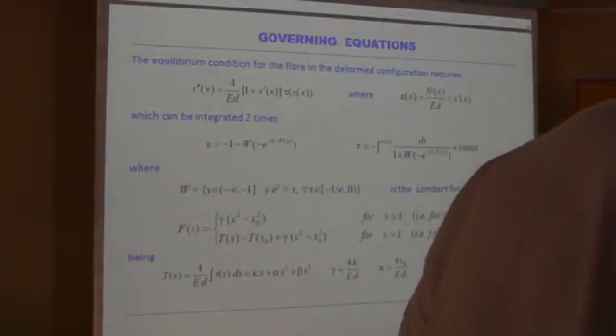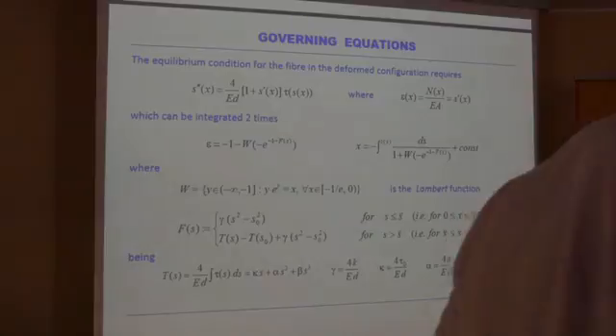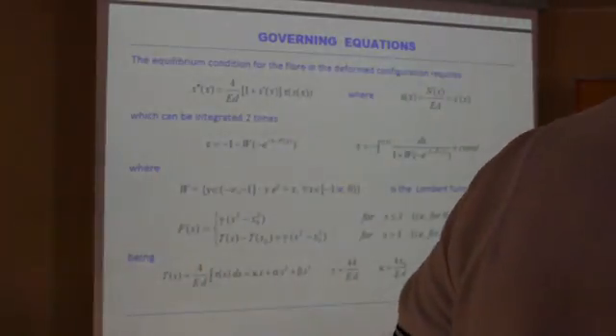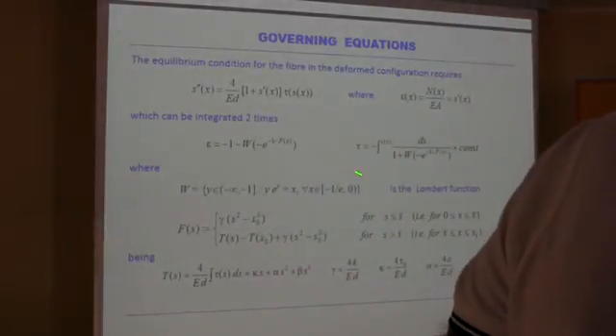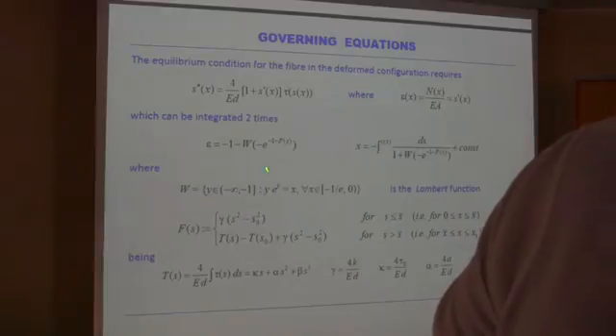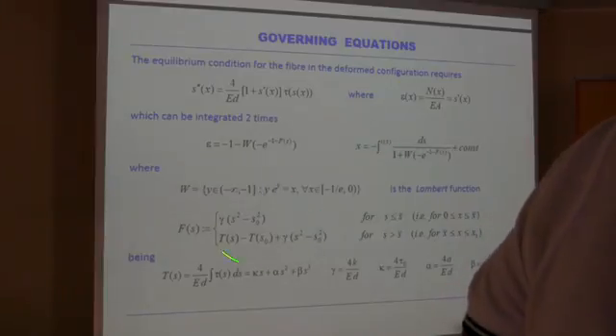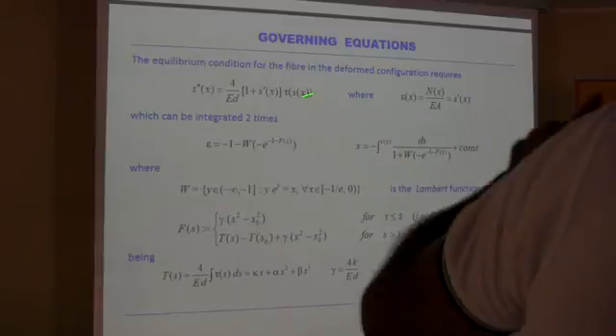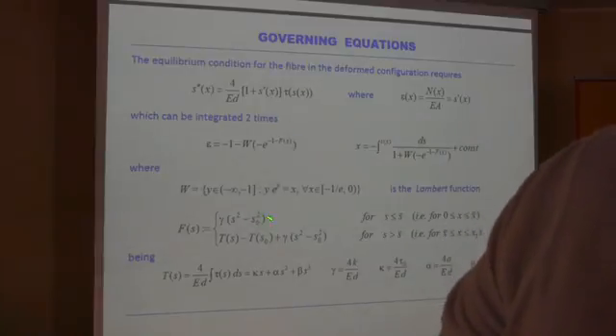So, by imposing the balance condition on the deformed configuration, we obtain a second-order nonlinear differential equation where this term is different for the bonded and the debonded part of the fiber. However, this relation can be integrated two times, and this is the Lambert function which appears in this integration. This term is different for the bonded and the debonded part of the fiber. However, they can be integrated analytically.